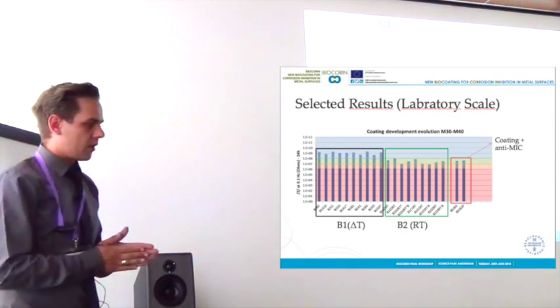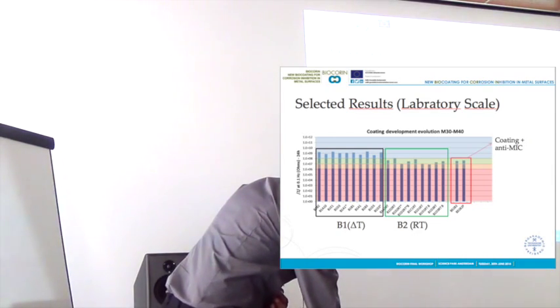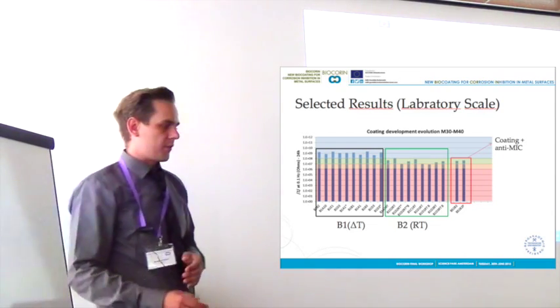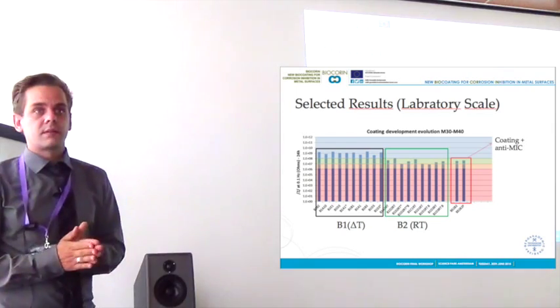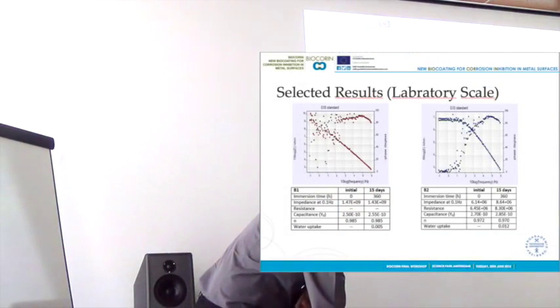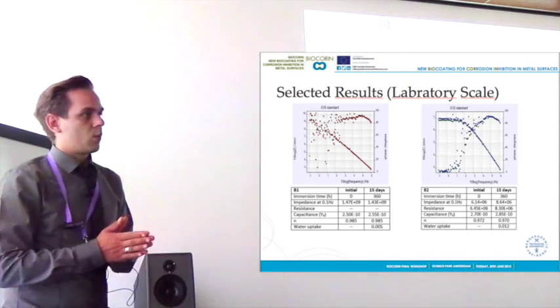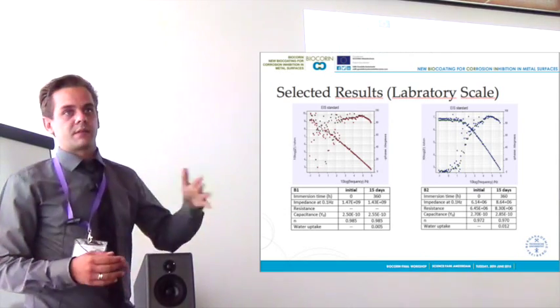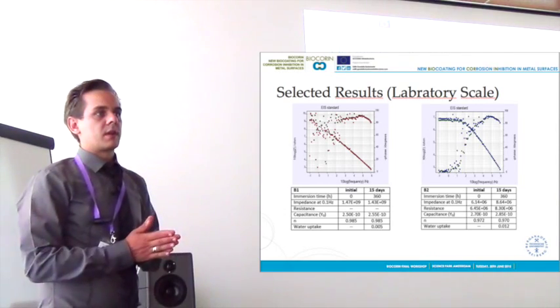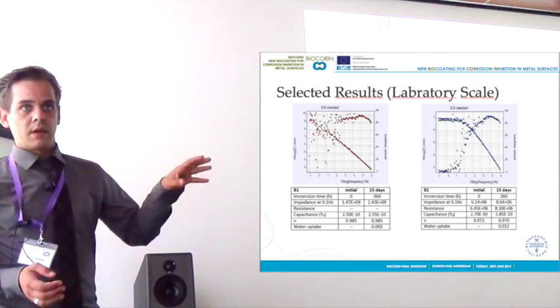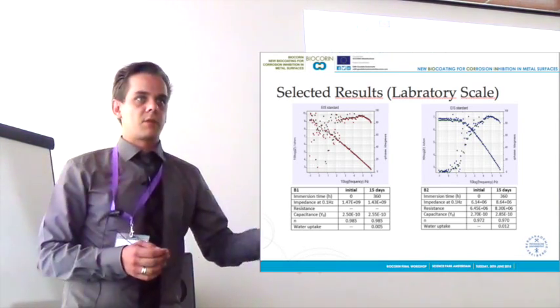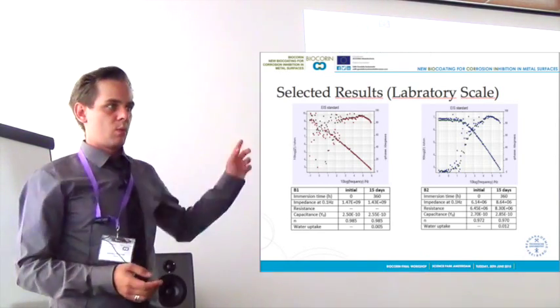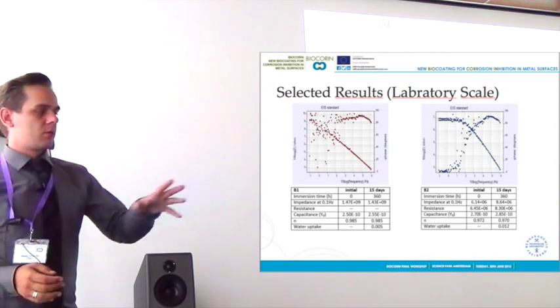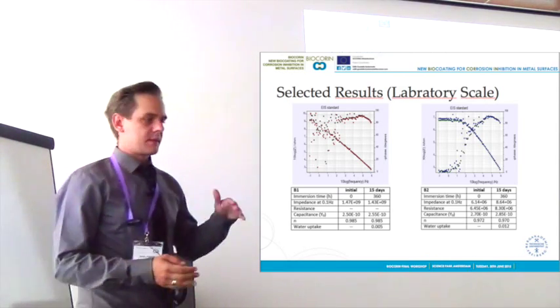Here we have some EIS results of B1 and B2 in comparison at the initial stage of immersion in saline water and after 15 days. Here you can see again that B1 is working quite perfectly. There is no decrease of the resistance, and B2 has lower barrier properties but doesn't decrease over time. We have more data for B1 that show that it even works well after more than 1 month of immersion. B2 is a very new generation. The last generation doesn't work that well. We will show that on the next slide, I think. But the new version is working quite well. So we have very constant barrier properties of the coatings, and that looks very promising.